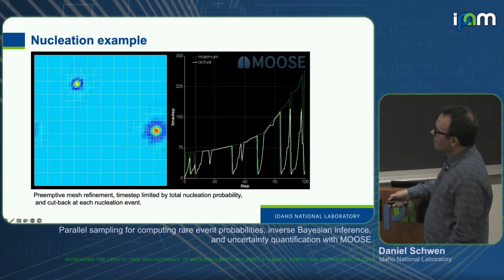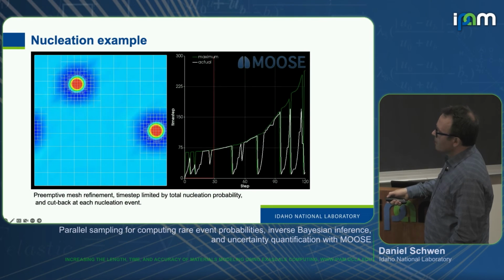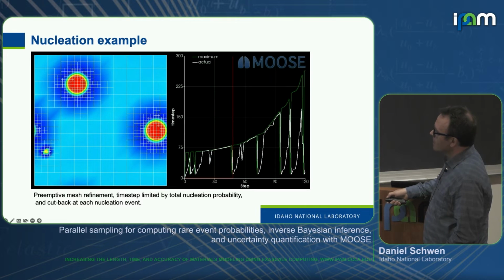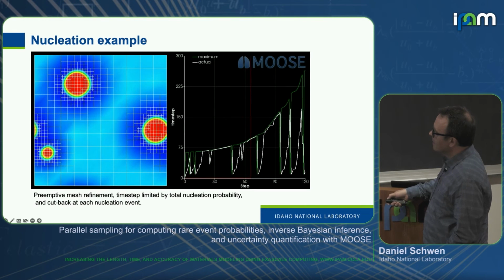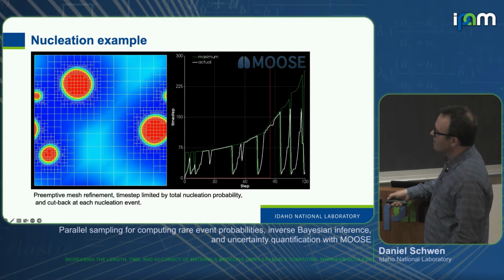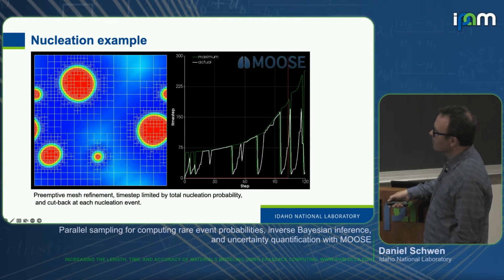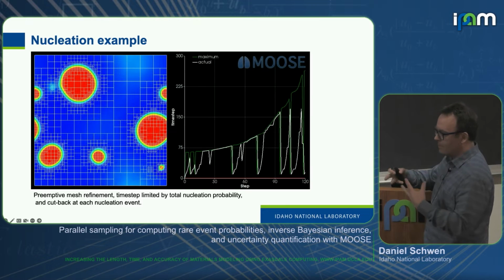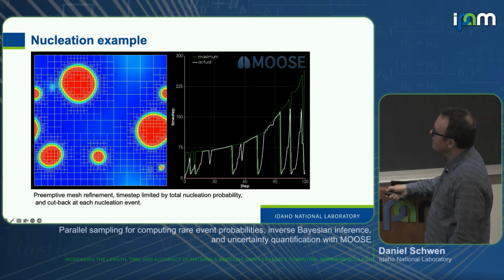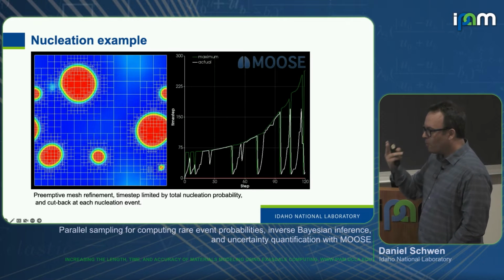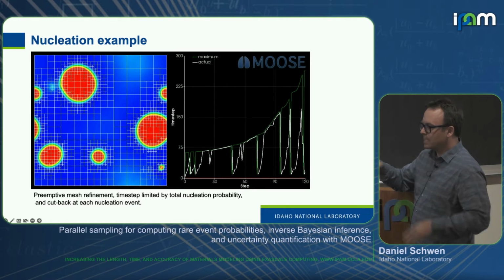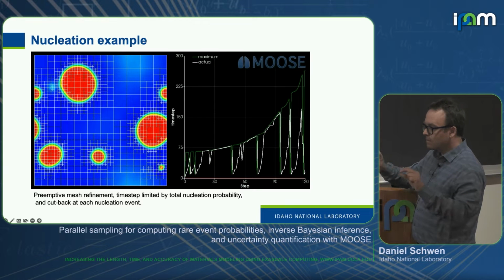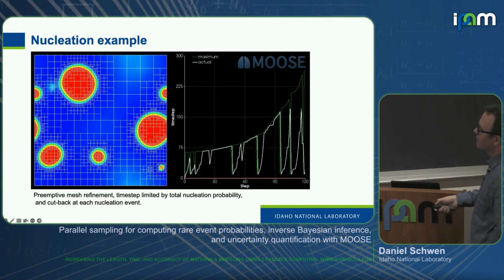Okay, and we know where we insert nuclei, so we can pre-refine the mesh, and we can deal with the time steps. We know that small particles with high curvature have very fast evolution, so we cut the time steps so that we capture the physics. And this upper limit for the time step here, we can also calculate by keeping the probability to have 2 or more nucleation events happening during one time step at a very small epsilon, okay? And that allows us to deal with that.